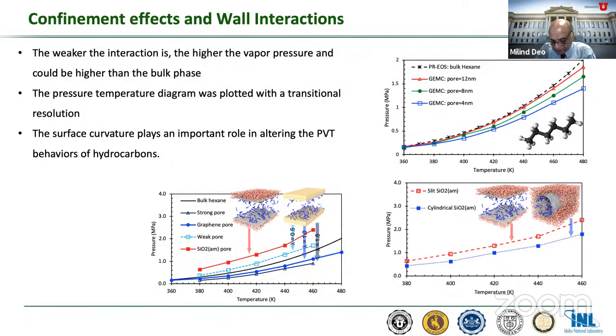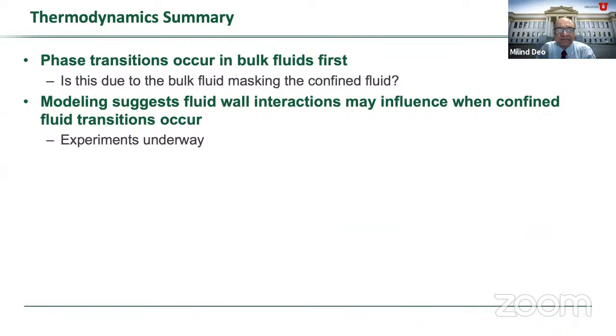And there are good theories and models to explain that. So again, the takeaway: phase transitions occur in the bulk fluids first. Is this due to the bulk fluid masking the confined fluid? This might be yes. And modeling suggests fluid-wall interaction may influence when the confined fluid transitions occur, and experiments are currently underway to test that hypothesis. So that's my thermodynamic piece. But it's quite exciting to look at these phenomena at various scales and using various experimental tools available to us.